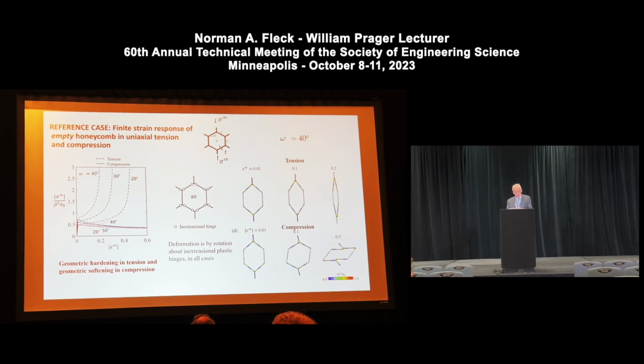If we take the same honeycomb and put it in tension, again, plastic hinges form. This is what you get if you take a hexagonal honeycomb, chicken wire, and pull it. You stretch it out, and geometric hardening takes place with lockup. And the rate of hardening depends upon the initial orientation, the initial value. It's delayed if omega is small, but in all cases you get this strongly stable response. So there's a strong geometric effect here, and I don't know how well appreciated it is, but many people just do compressive tests, get these crush bands. But the tensile response is very different from the compressive response. This is for the empty honeycomb.